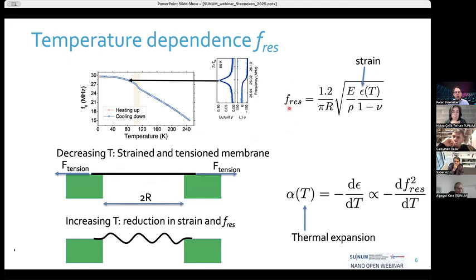By monitoring this resonance frequency, we can calculate how much strain and stress there is in the membrane. And by looking at the temperature dependence of this resonance frequency, we can also get the thermal expansion coefficient. That can be calculated by this equation. It's basically minus the temperature, the resonance frequency squared, the derivative of the resonance frequency squared towards temperature. If you increase again, of course, it expands again and the frequency goes down.